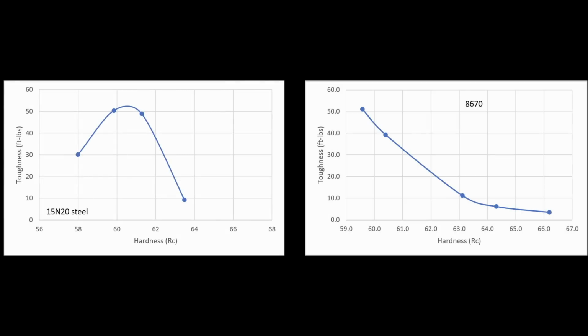However, when it comes to high hardness, I've seen this trend with some bladesmiths in recent years, that they take something like 15N20 or 8670 and they temper it at a low temperature to try to get 63, 64 Rockwell, because they say, well, this is a high toughness steel, so I will temper it to a high hardness and get the benefit of high toughness and high hardness.